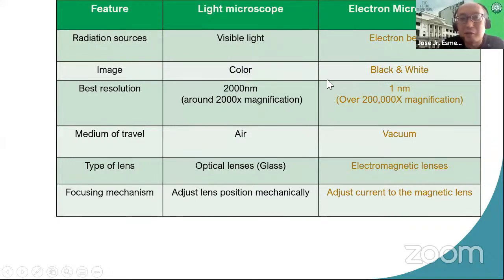In the electron microscope, you use an electron beam. In the optical microscope, you can see the actual color of your sample. But in an electron microscope, it's black and white because you only see the contrast, because these are scattered electrons processed by the detector. The best resolution you can get from an optical microscope is only around 2000x. The resolution for the electron microscope is about 1 nanometer, about 200,000 magnification.